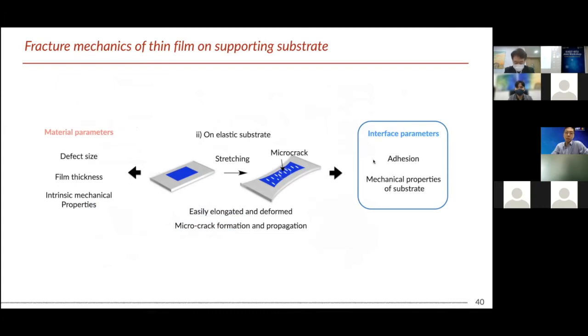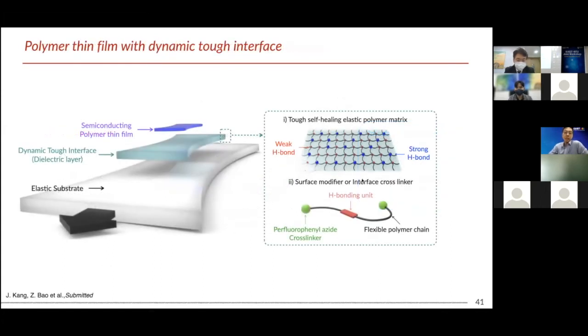So I just focus on how we can improve the interface parameter in the stretchable electronic system and see how it can change the fracture mechanics behavior of the semiconducting polymer film. So here's a scheme where I make a very tough interface with self-healable properties. Basically, I synthesized a new interface material. It is composed of two components. One is a self-healable polymer matrix, and the other is an interface cross-linker to promote nice cross-linking between the two different polymer surfaces.